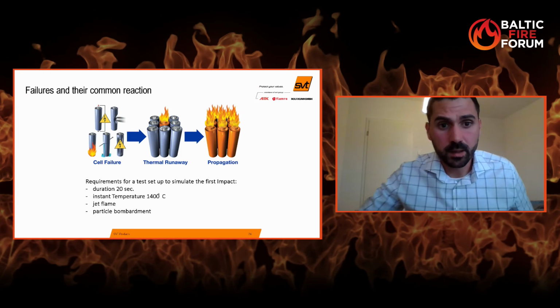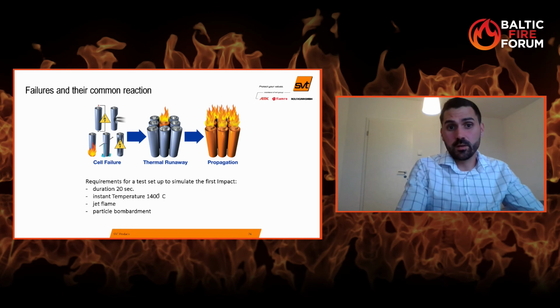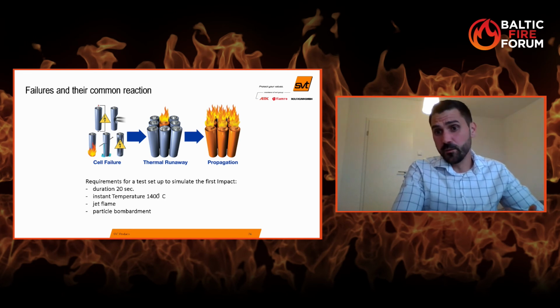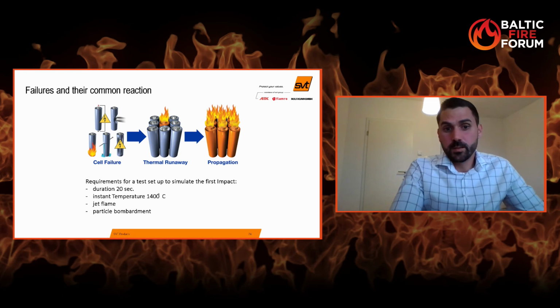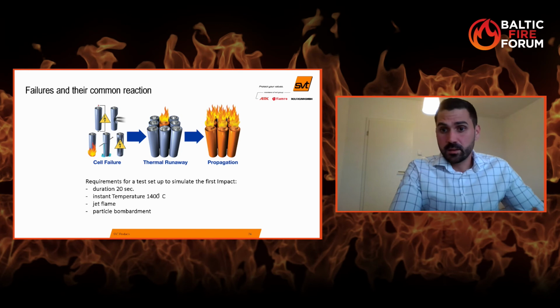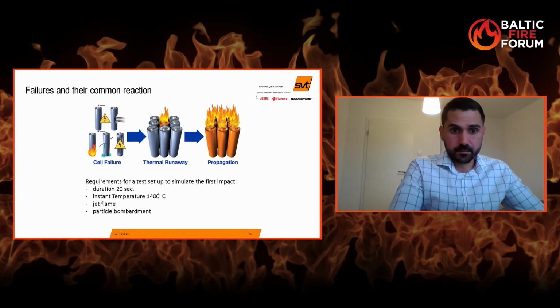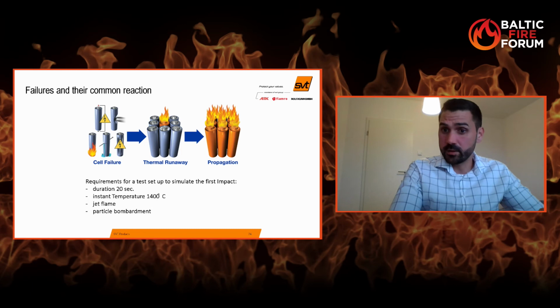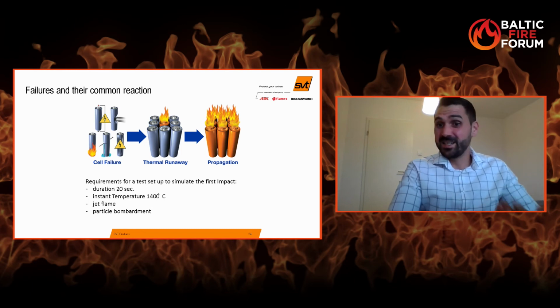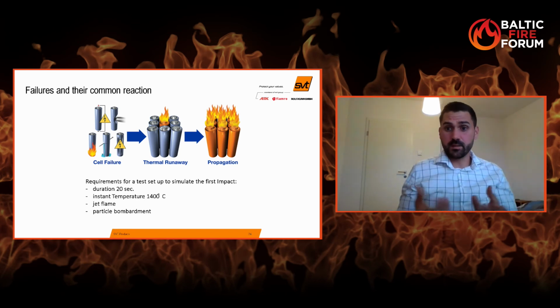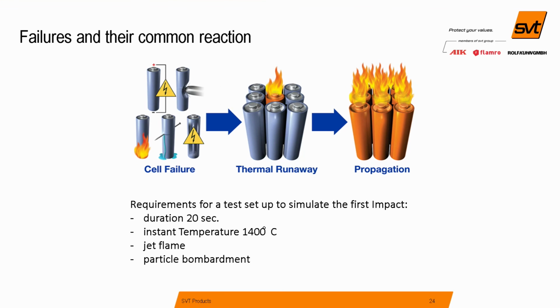You can see right now what we have to do for these tests, but what are the requirements for these tests? As we know from our customers and from some self-knowledge, we have requirements for a test setup. If a cell goes through thermal runaway, we get a reaction of about 20 seconds. 20 seconds is the time range in which the cell reacts. We get an instant temperature of 1400 degrees, like a jet flame with particle bombardment. All the particles inside the battery come out through a small hole like a jet flame and penetrate the substrate. So these were the requirements for our test setup.